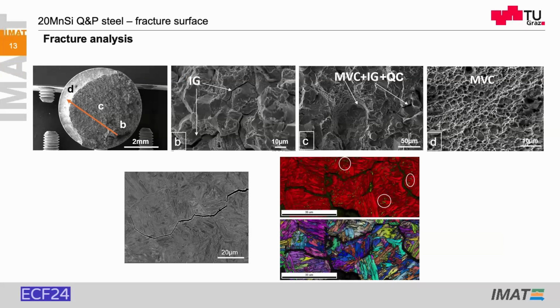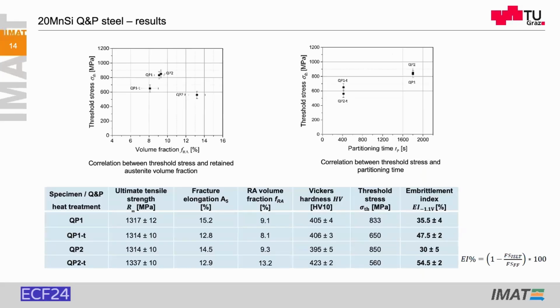Yeah, the fracture starts intergranular and turns to quasi-cleavage plus microvoid coalescence and ends with microvoid coalescence. There is no correlation visible here to the retained austenite distribution. Yeah, this is the nice outcome that we have a quite low hydrogen embrittlement index with this long partitioning time. As you see here, the threshold in the incremental step load test is quite high. So this has a nice potential for these screws.